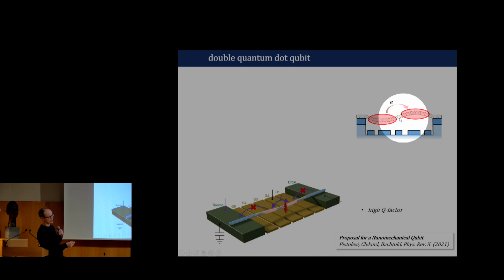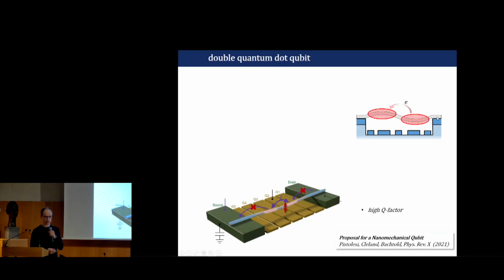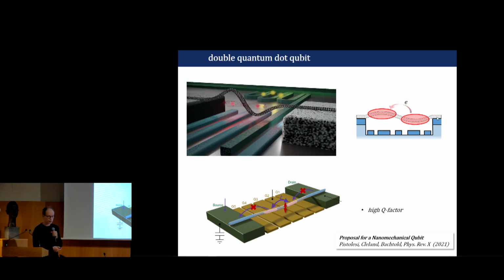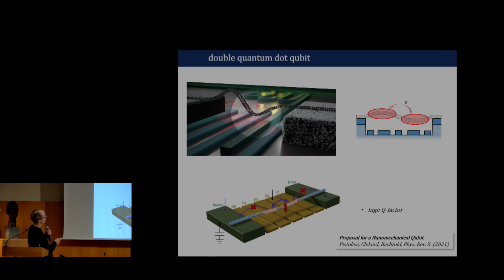But on the other side, I explained before that we were detecting the vibrations by measuring current noise through the nanotube. So if we cannot measure the electrons flowing through the nanotube from this reservoir to this reservoir, we cannot detect the vibration. So we had to develop a new technology, which is to use a superconducting resonator, and that is shown here. So we use radio frequency photons at about 1.5 gigahertz to detect the vibrations.